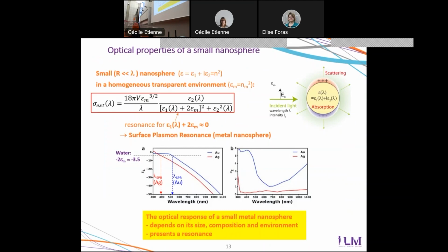So you see there are a few parameters in this expression. There is the volume of the particle, the wavelength of the light here, and the dielectric function, which is just the square of the refractive index with which you may be more familiar, of the particle itself. So it's a complex quantity because the particle is generally absorbing, and the environment. So it's a real quantity if the environment is transparent here. So a first key message is that the optical properties of a nanoparticle depend on the composition of the particle itself, but also on the environment around it.